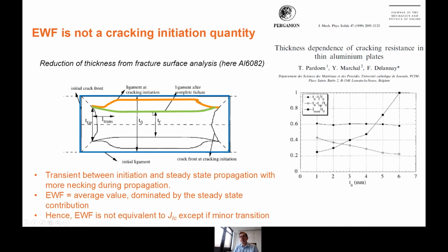And the green is what you measure on the fracture surface at the very end of the test. If you take the specimen, you measure a reduction of thickness, which is TF. So the initial thickness was T0, and the final thickness you measure on the fracture surface is TF. And this reduction can be very high. If you want to see numbers for this aluminum alloy, and this is the same on many steels, you see that (T0 minus TF) divided by T0, which is the relative reduction of thickness, is 0.6 in that aluminum alloy, so a 60% reduction, which is quite high.